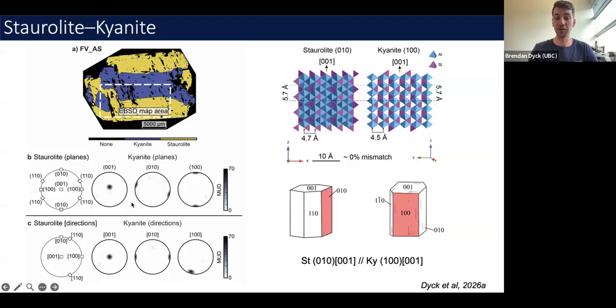And then down in the bottom of these pole figures, what I'm going to do for all these subsequent slides is rotate all of the parental phases into a common reference orientation. Now I'm going to apply the exact same rotation on a pair by pair basis for all the adjacent daughter crystals. So in this case, there's a single staurolite and a single kyanite, so we're just going to rotate our staurolite and the kyanite will have that same rotation. But in subsequent examples, we might look at hundreds of these grains and then look for patterns in those post-rotation orientation relationships.